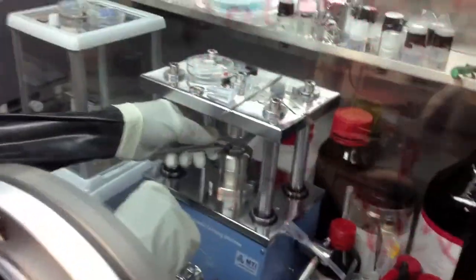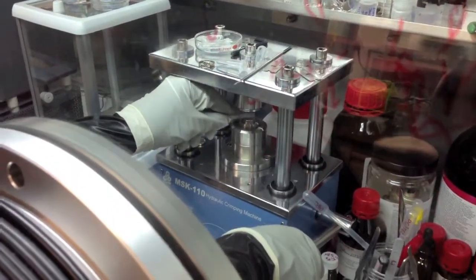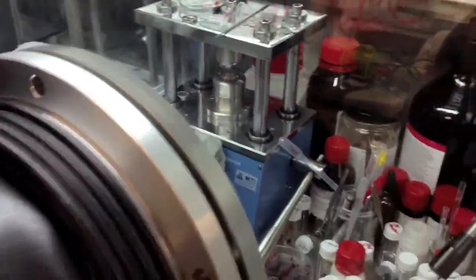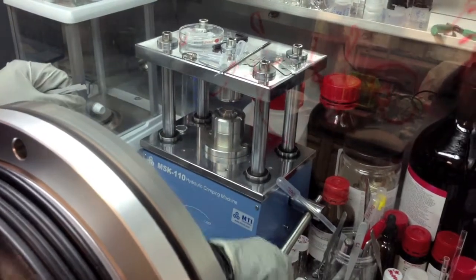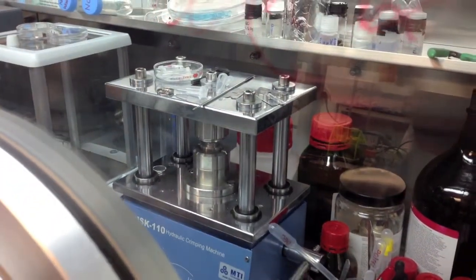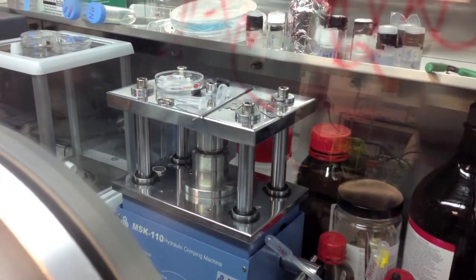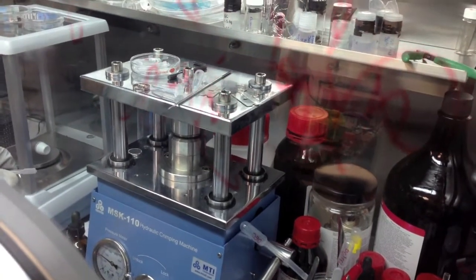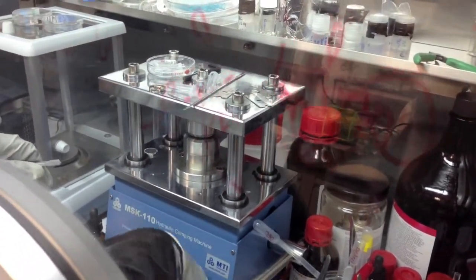After the half cell is assembled, it is placed into the hydraulic crimping machine and pressed at a pressure of 750 psi. After the pressure is released, the cell is inspected for any electrolyte leak. If there is no leak, then the half cell is removed from the glove box for electrochemical testing.